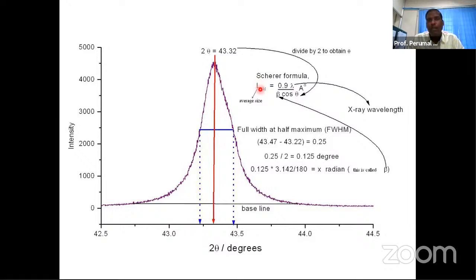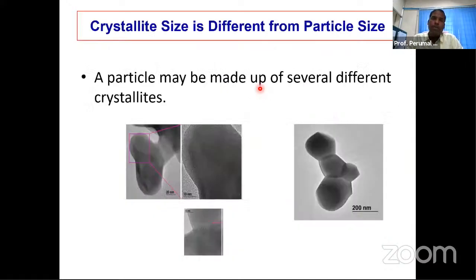This is typically in angstrom. If it is a very small size, you can give it in nanometer. You can obtain the crystallite size. What is that crystallite size? A polycrystal consists of several crystallites. That average crystallite size is what you can get from X-ray diffraction. Many a time people confuse crystallite size with particle size and grain size. This is the difference. The size that you get from X-ray diffraction is known as crystallite size. But the size you get from a microscope is the particle size or grain size. A particle may have many crystallites, or a grain may have many crystallites.